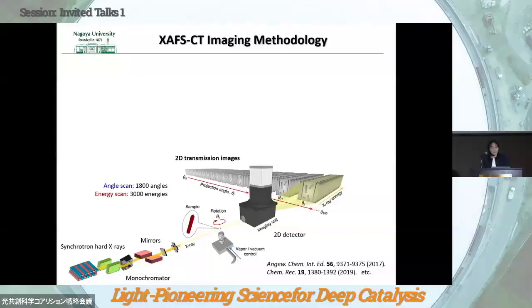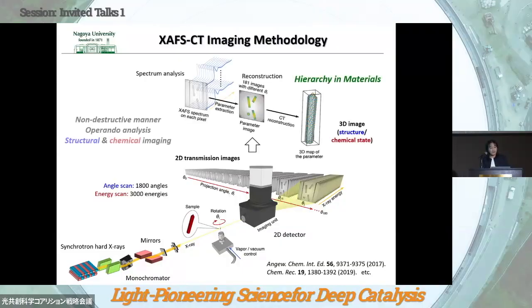So monochromatized X-rays were irradiated to the samples, which sit on a rotating stage. We recorded the two-dimensional transmission image of the samples at different angles. This is a simple CT technique, and you get a series of 2D transmission images at different angles. And then we scan the energies for the XAFS spectroscopy measurement.